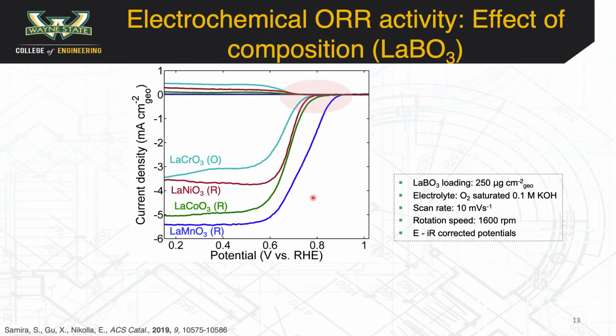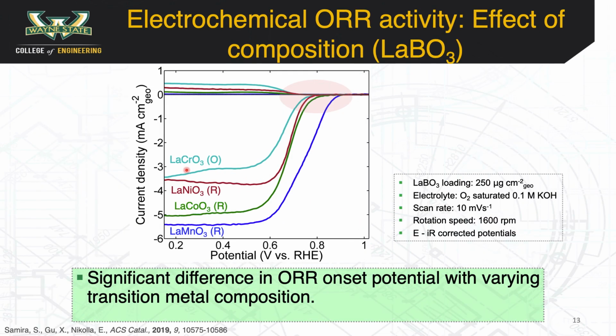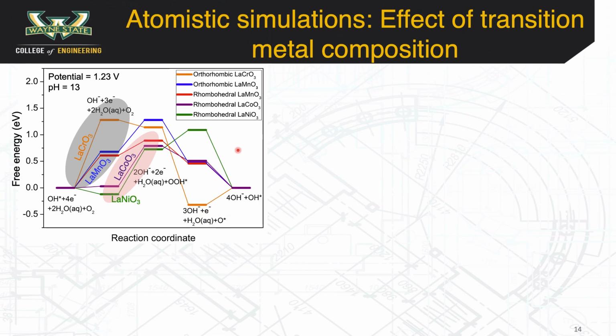We then study the effect of the B-site composition in these oxides while varying the B-site from chromium to nickel. A significant difference in the ORR onset potential is observed, suggesting that the electronic structure of the B-site cation in these oxides plays a crucial role in determining the electrocatalytic activity.